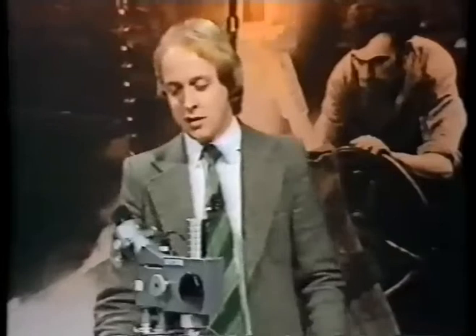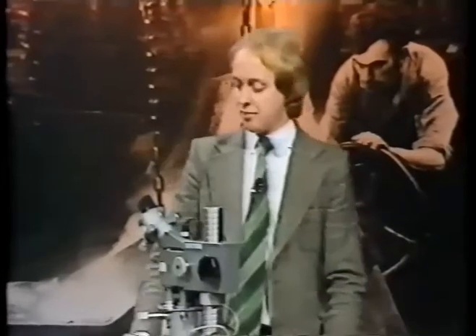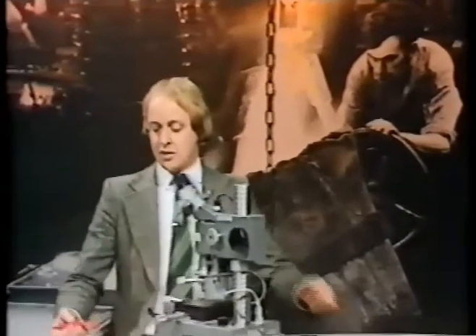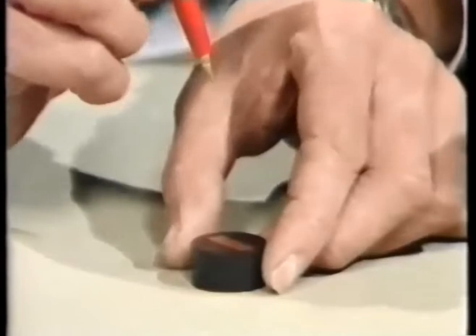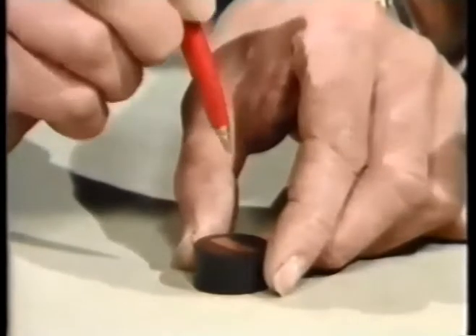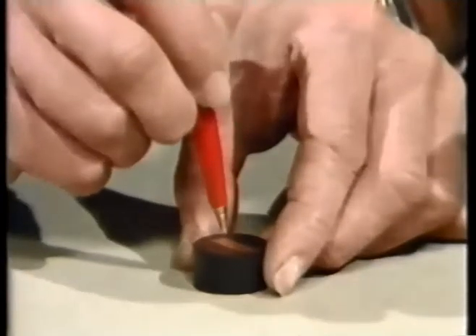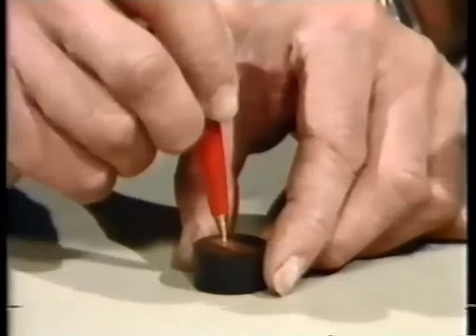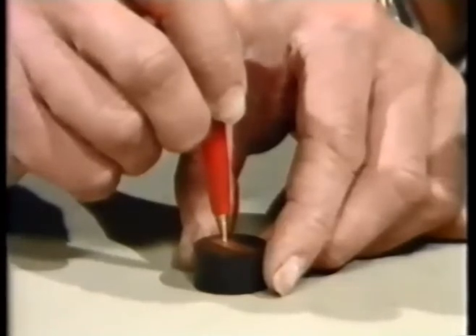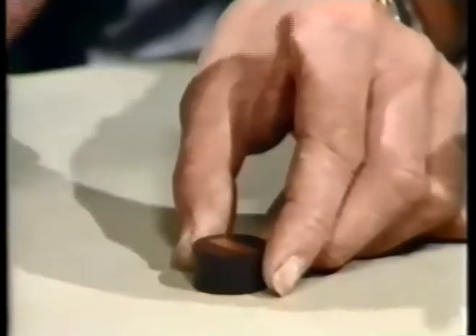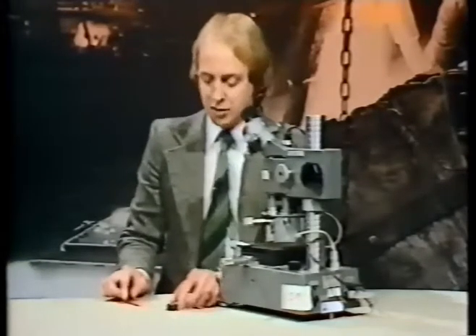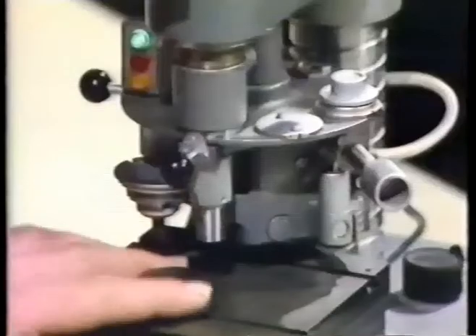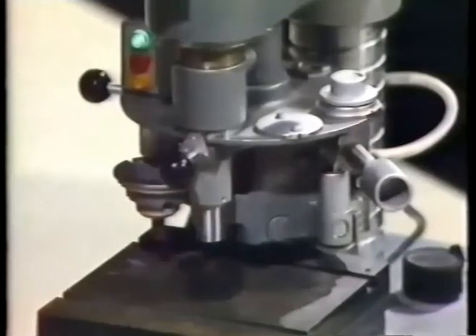We can check that by using equipment like this, which is a microhardness tester. And briefly, this will bring a diamond stylus into contact under a given load to indent the surface of a metal for a given time period, and then remove the load. We will leave an indentation. The larger the indent, the softer the surface of the material. So I can select my region of interest,